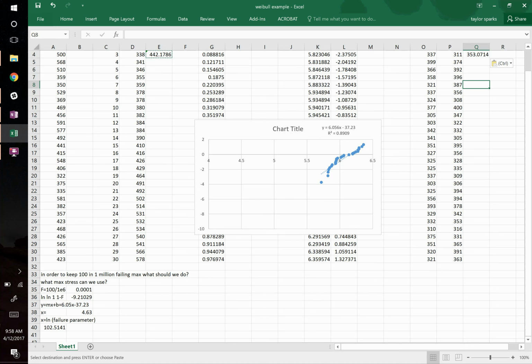At first blush, most engineers would say, if I don't want this thing to fail, let's use this stuff, right? You all agree? And it seems like a better choice. Tell me why this is maybe not a better choice. Designing for failure. If you're doing probabilistic design, why could this material on the right be a better choice? Having probability of failure due to that. Yeah, basically this is a tighter distribution than this one, which means if you need very, very few to fail, you're actually going to find that this one's better. Let's prove it, right?